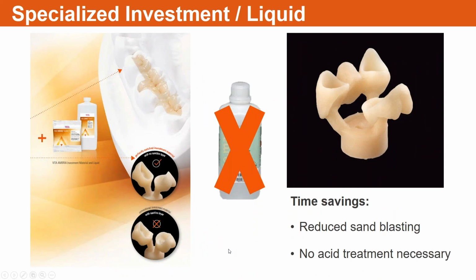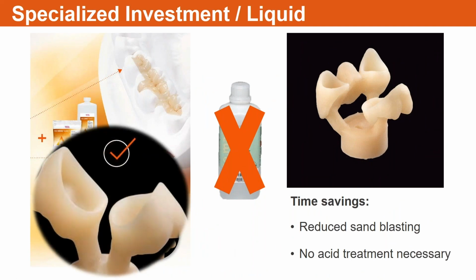But we did spend a lot of time developing this investment liquid. When you have a phosphate bonded type investment, during the process, as you press this lithium disilicate inside your molds, that lithium disilicate has a tendency to adhere to a phosphate bonded type material, and then it just strips it off at the end. So that's why you have what we call the reactive layer. The liquid that we use, at least on ours, pretty much eliminates all of that reactive layer. So it comes out really nice and clean, and you don't typically have to use an acid to try to remove that reactive layer at all.